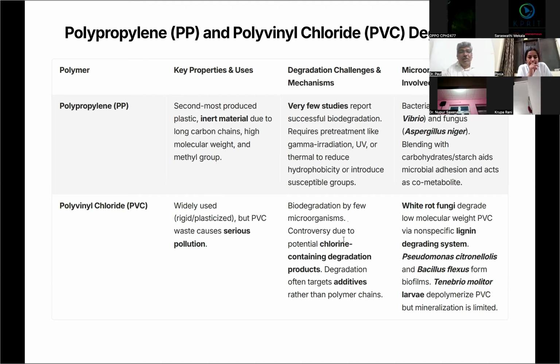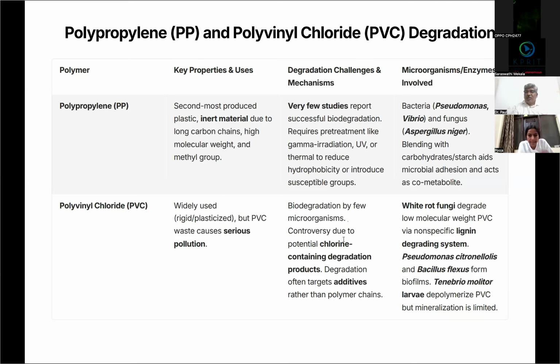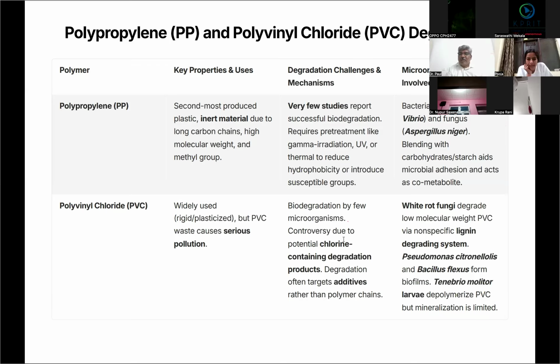Coming to polyvinyl chloride. Polyvinyl chloride is a very rigid plastic which we regularly use in households, and not only that, polyvinyl chloride is mixed with several additives which make it more recalcitrant. But there are certain lignin degrading fungi or mushrooms which can degrade PVC in very small amounts. And certain bacteria like Pseudomonas citronellolis and Bacillus flexus, and some insects, Tenebrio molitor, in the form of their larvae, can depolymerize PVC and mineralize it in a limited quantity.